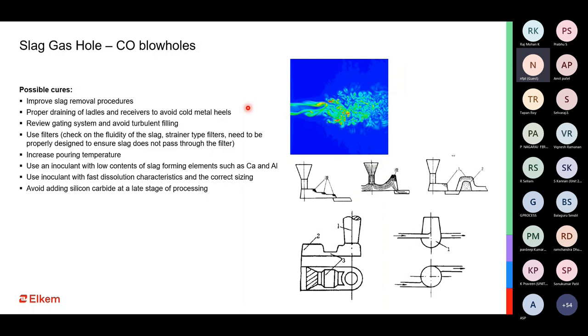Like I mentioned before, we have to avoid adding silicon carbide at a late stage of processing, because silicon carbides have a high melting temperature, which can just stay as inclusion, slag inclusion, in the system.